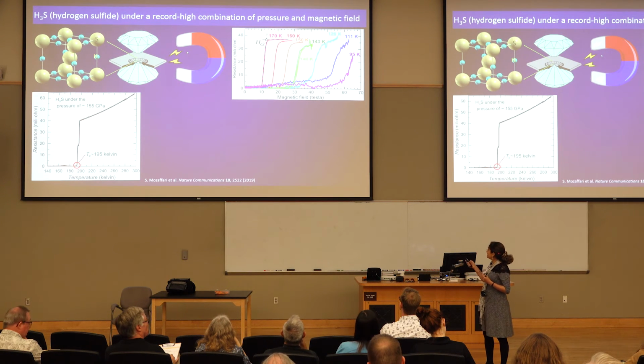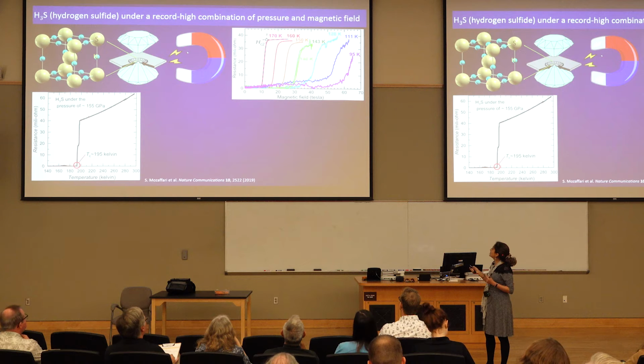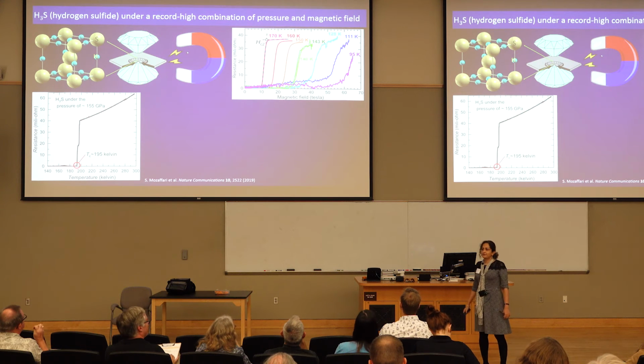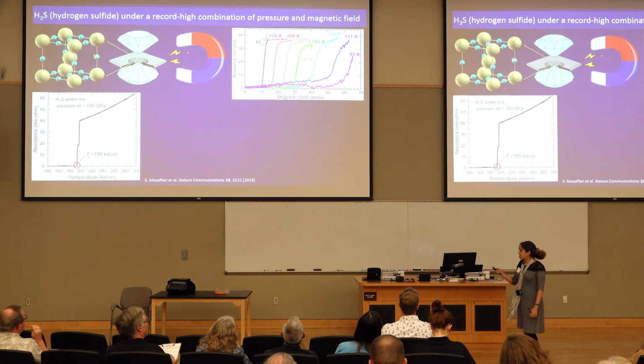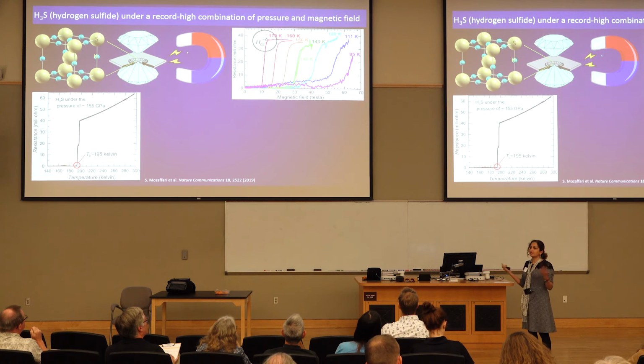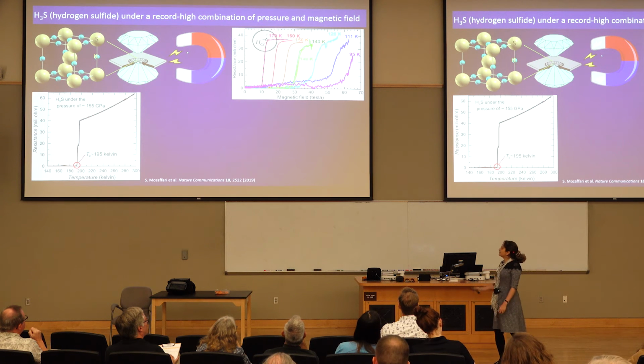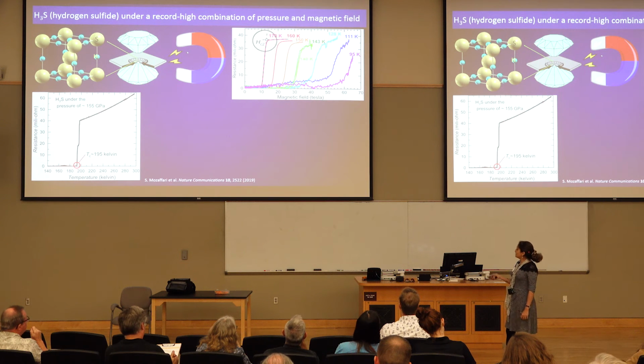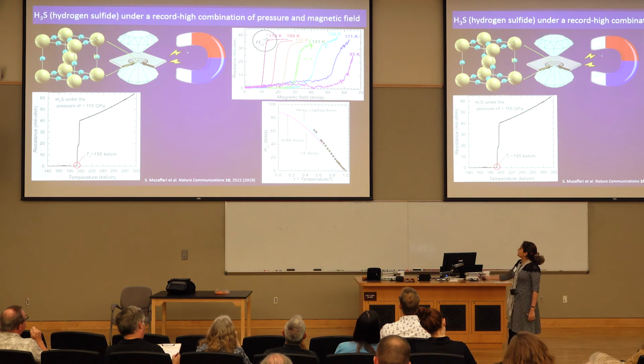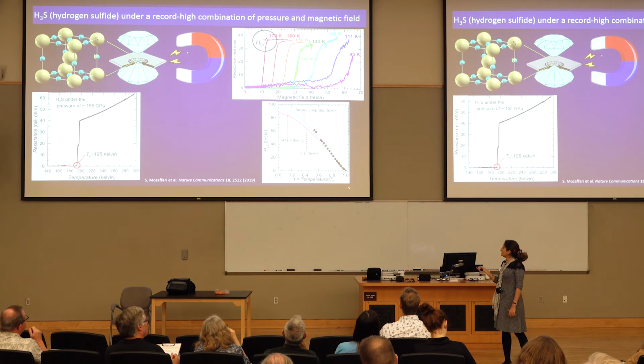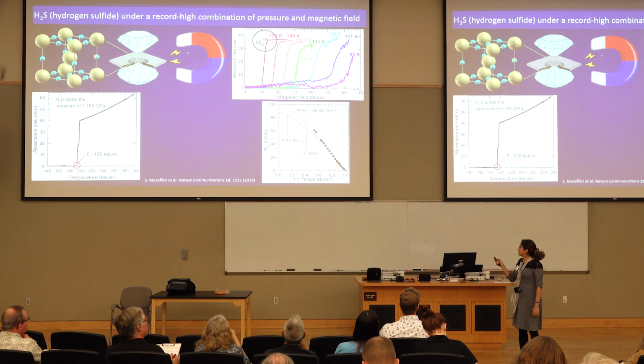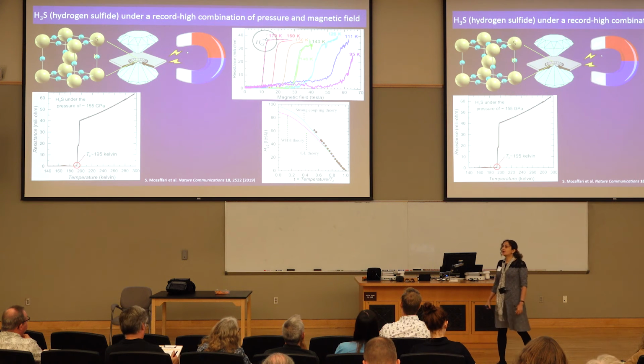So in our measurement, we kept the system at a constant temperature, for instance, 170 Kelvin, and then we slowly ramped the magnetic field. We then recorded the field at which superconductivity is destroyed and the material shows a non-zero resistance. That field is called the upper critical field, or HC2. We repeated the measurement for several temperatures and plotted HC2 as a function of reduced temperature. We then fitted our data to 3 different theoretical models and found that H3S is best described by this blue line, or a strong coupling theory.